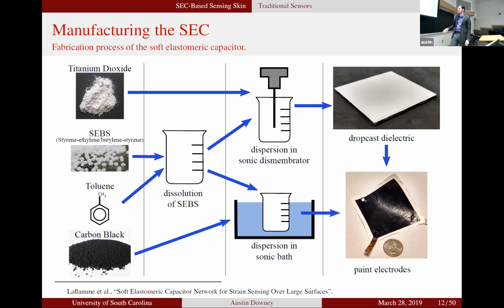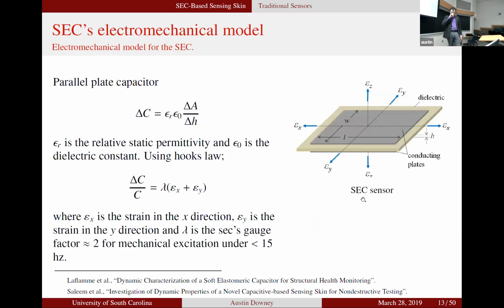And that conductive layer on each side forms a capacitor with a very simple electromechanical model. So we can get a change in capacitance as a function of our relative static permittivity and the dielectric constant multiplied by the area over the height. And so a change in area and a change in height when we stretch the capacitor will give us a change in capacitance. And it's an additive strain, epsilon x plus epsilon y, with a gauge factor of about 2.